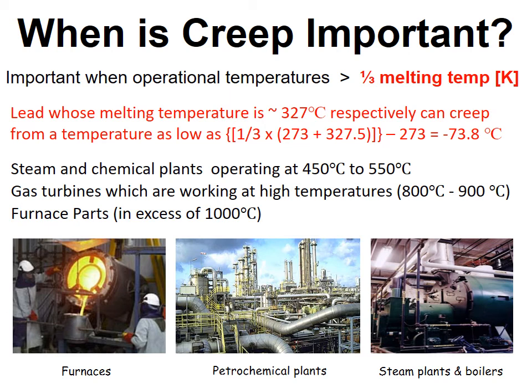So the question now is, when does creep become important? It becomes important when metals and alloys are stressed at a temperature in excess of about 1/3 the melting point in Kelvin. For example, lead and tin, whose melting temperature is approximately 231 degrees and 327 degrees respectively, can creep at room temperature, while molybdenum, tungsten, and nickel-based alloys creep at about 1000 degrees Celsius.